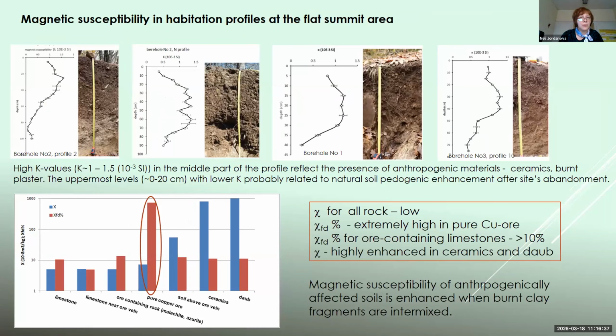The next susceptibility profiles we measured at the top of the hill where the ancient miners were living during the mining operations. And at these sites, we obtained much stronger enhancement in magnetic susceptibility at the middle part of the profiles, which was a result from different additions of anthropogenic materials into the soil. And these materials were mainly ceramics, burnt plaster, or daub. And uppermost, about 20 centimeters of the profiles are relatively weakly magnetic, and we interpret this as reflecting the natural soil formation after abandonment of the mining site.